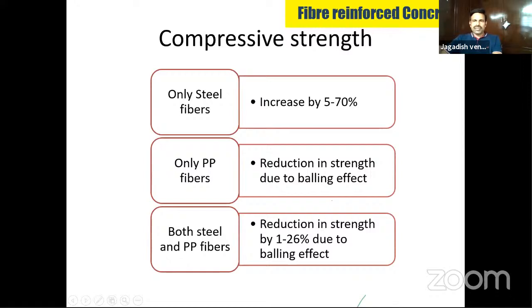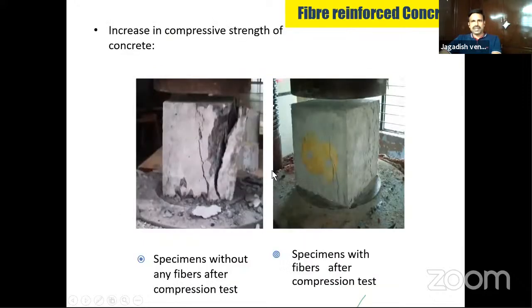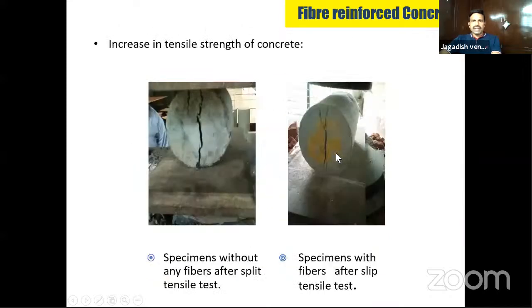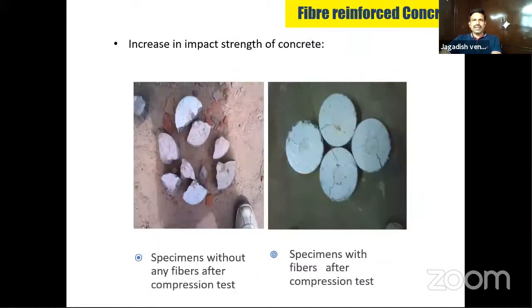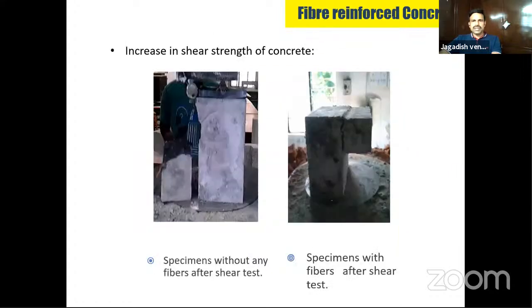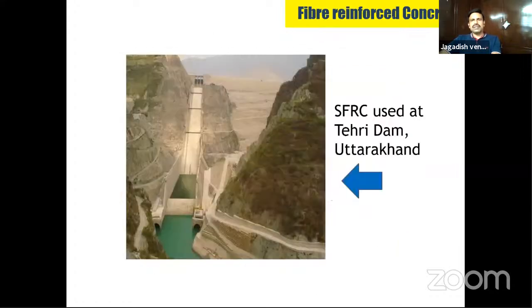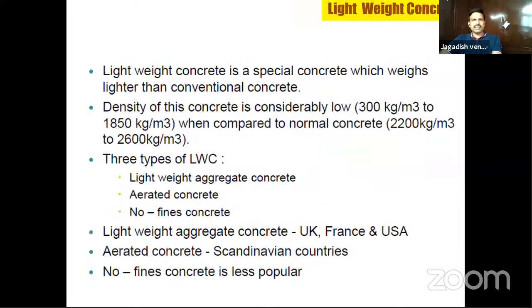Based on the review of literature or various works, typically when polypropylene and steel fibers are used, these are the results, particularly on compressive strength. You can see it holds. The fracture behavior of the concrete, when you use the fibers, even the tensile strength, it holds. The crack behavior changes completely. The impact strength: it holds the concrete in place, so if you use the fibers, it also contributes to the impact strength. Shear strength. Some of the applications are like Tehri Dam in Uttarakhand.